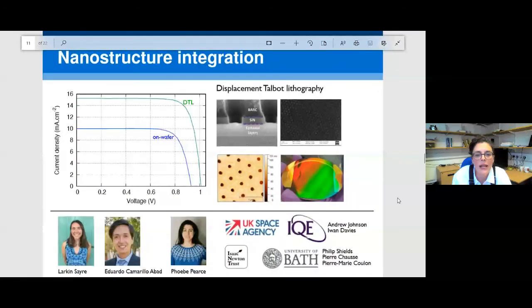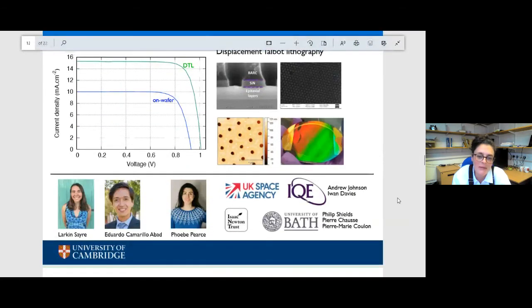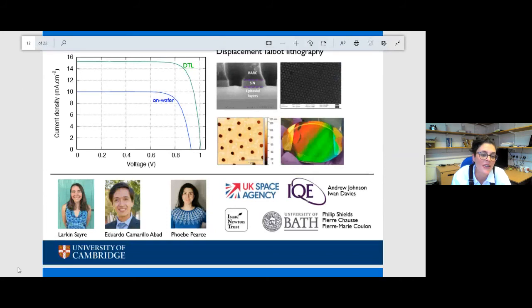So I've got some results for you here, hot off the press. What does displacement Talbot lithography do for our devices? This data set was acquired by Larkin just on Monday, so this is really very new. We can see what we have in terms of current voltage curve here for our on-wafer devices. By integrating that same device with the displacement lithography pattern, we get around a 50% bump in terms of our current density, and also, really excitingly, a really nice improvement in terms of voltage, exceeding 1 volt VOC.